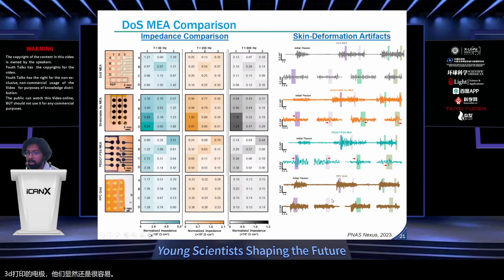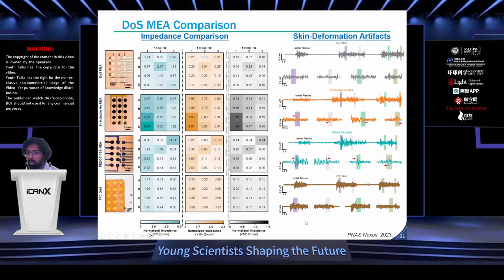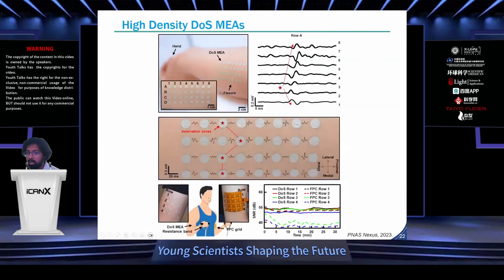Now, the last point here is that the FPC grid actually shows no artifacts in this test, but it should be noted that they have extra adhesive layers. And after a few hours of wearing, not as strong and eventually with artifacts.